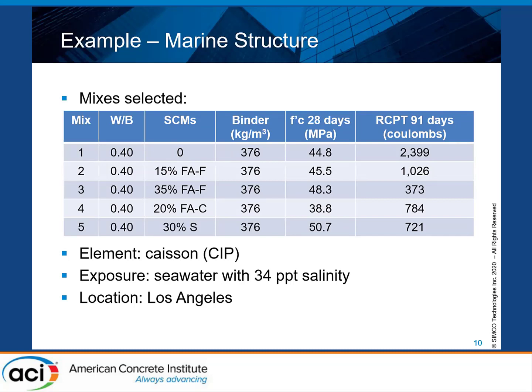The lowest that we get is 38.8 for a mix with 20% fly ash of type C, class C fly ash, sorry. And if you look at the RCPT, which is an indication of the chloride penetration resistance, you see that the mix without SCMs is much higher, almost 2,400 coulombs. But when you start using SCMs, you get much better resistance to chloride penetration. And we even have a mix below 400 with the one with 35% of class F fly ash.